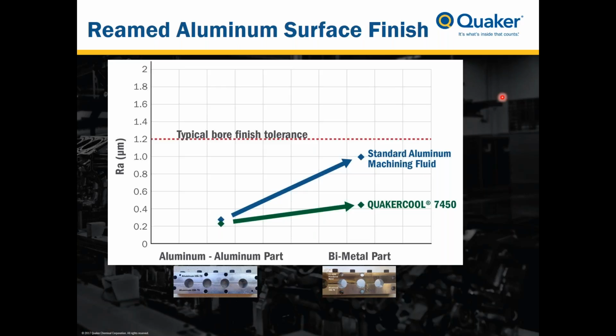The interesting result was, as we showed before, that the standard fluid on the bimetal part resulted in a very noticeable degradation of the surface finish. Again, up at 1. The newer developed fluid, QUAKERCOOL 7450, shows a marked improvement in the surface finish, the ream surface, obtained when the reaming of the bimetal part was conducted. Granted, there was a slight degradation, a slight increase from about 0.28 up to about 0.442. Nevertheless, both of these surface finishes are very good.